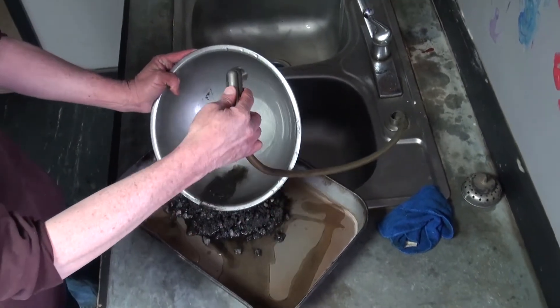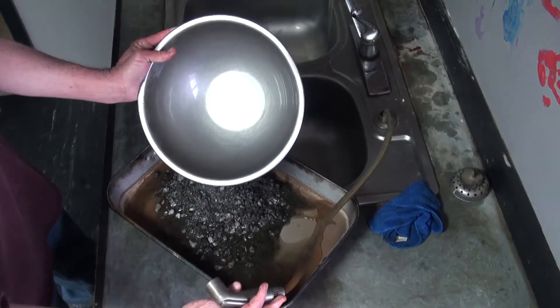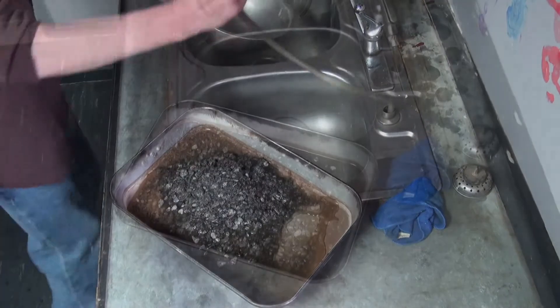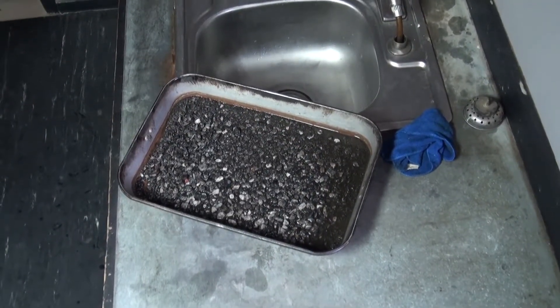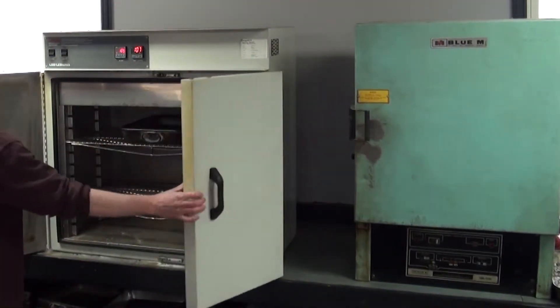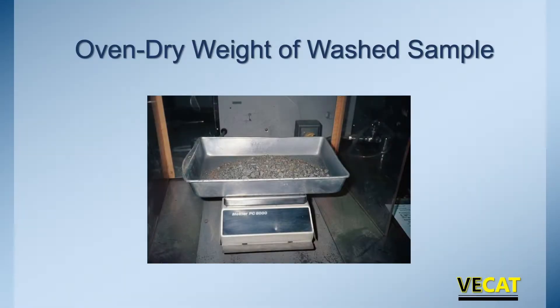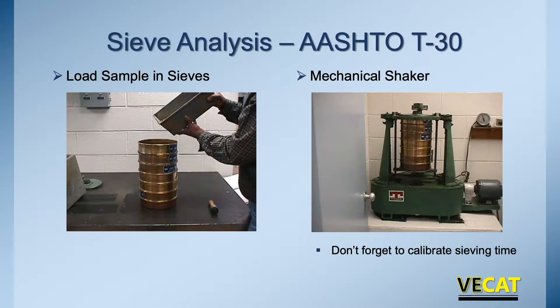Keep all the sample in your pan and take time to rinse it out clean. Spread the washed sample out so it dries as fast as possible, then transfer it to an oven and keep it there until dry. Once the oven-dry sample is cool, record this weight as the weight after washing.